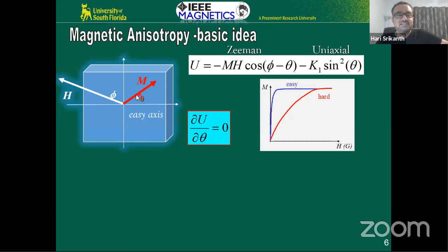And then you can see that this interaction can be represented by a simple equation here. Remember, I'm a physicist, so I have to show at least one equation. So this is my equation slide. It's a fairly simple equation. Basically, what it tells you is that the total energy is a competition between the external field, which is the Zeeman term, and the internal magnetic energy, which is this part here, and that's the anisotropy energy. Anisotropy is very important because it determines the shape of the magnetization curve. For example, whether you have an easy axis of magnetization or a hard axis of magnetization, whether you have a soft magnet or a hard magnet, it's all determined by the competition between the external field, the Zeeman energy, and the internal energy, which is typically the crystalline structure and other aspects, shape, for example, that could lead to the effective magnetic anisotropy.